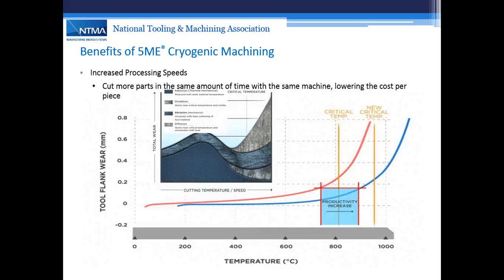And then there's a point there, it says critical temperature, where it's decided that if you go beyond that, the tool life is extremely short, and it softens the carbide. For example, 815 degrees Celsius is when the cobalt in carbide softens, and it becomes a little ridiculous to try and machine after that temperature. So what Frederick Taylor taught us back in the 1900s was machine as close as you can to that critical temperature without getting too close, to get the maximum number of parts off your machine tool with a reasonable tooling cost.